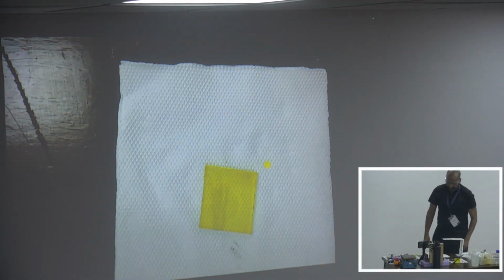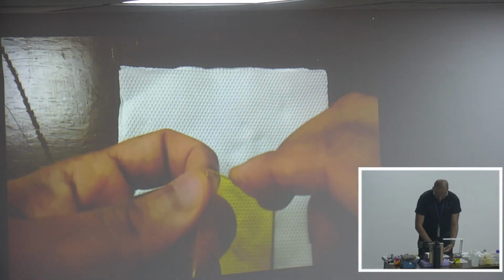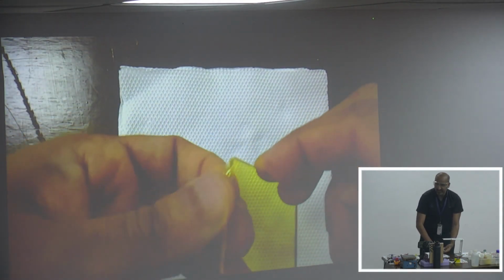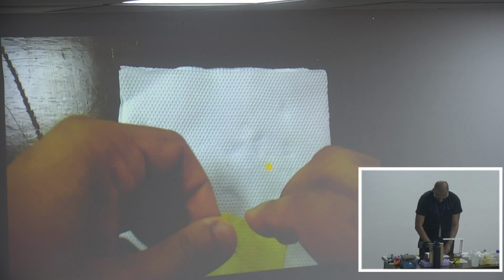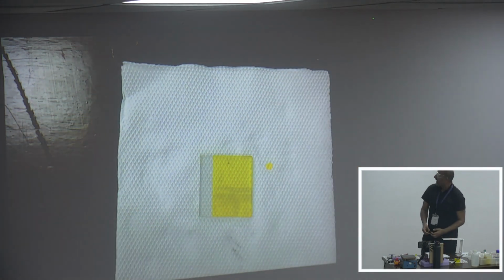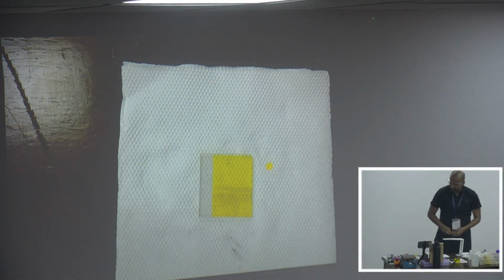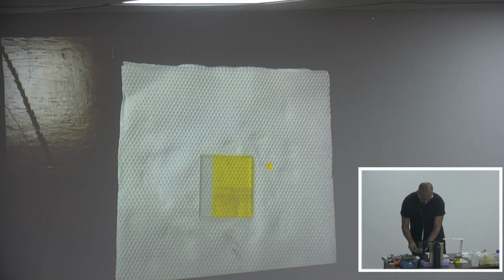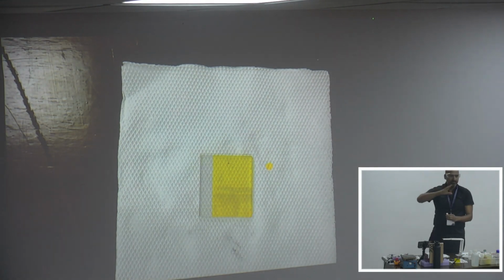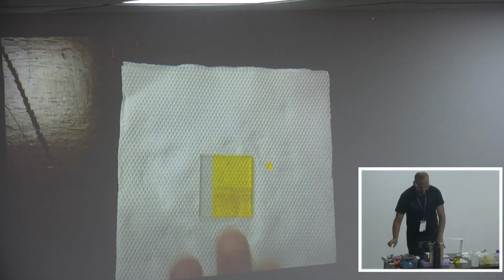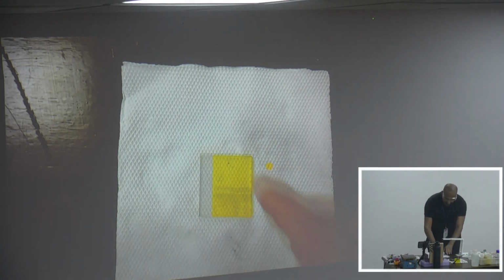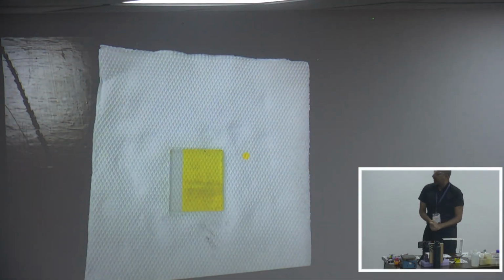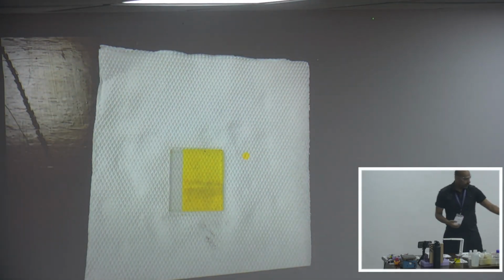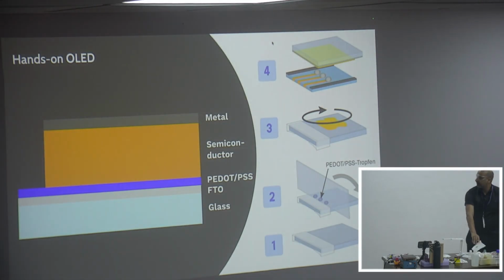And there you go. We have spin coated for only €2, so instead of 3,000 euros. So this is the cheapest spin coater maybe, and it works like a charm. So the layer thickness we have checked varies between 70 and 120 nanometers. So on some points it may be thicker, and on some points it may be thinner. So the last step: now we have achieved the semiconductor layer, and now the metal layer is missing.